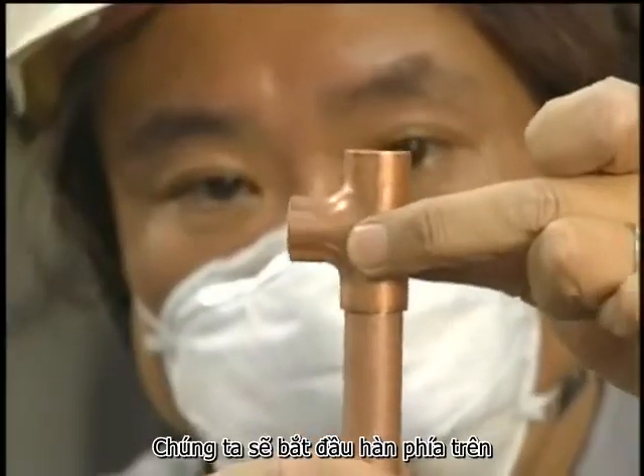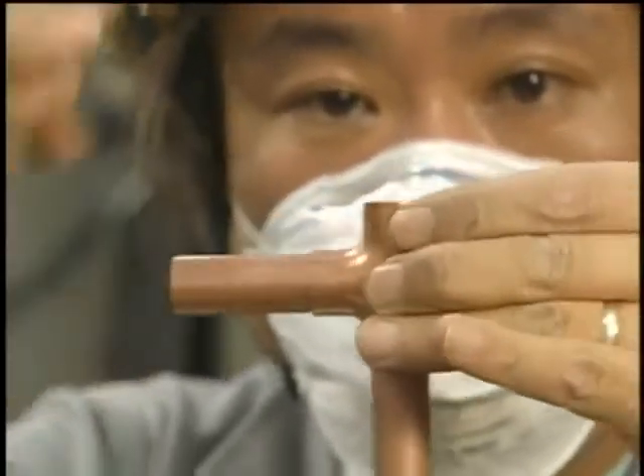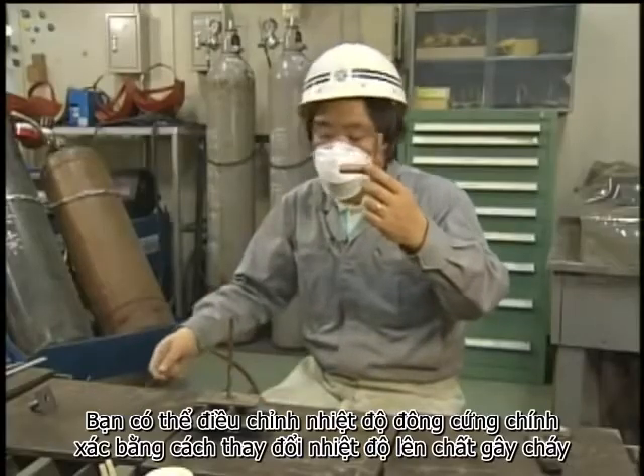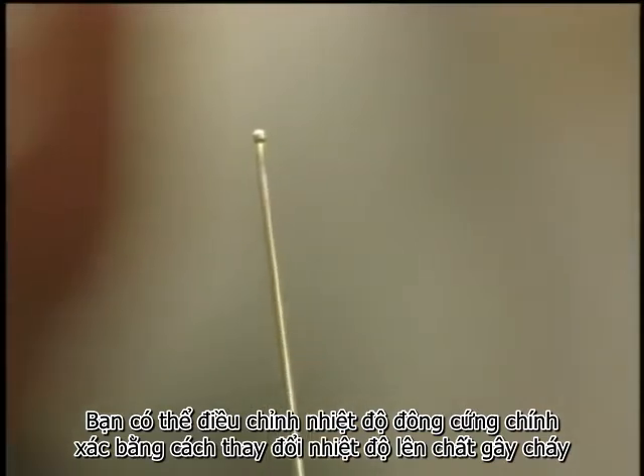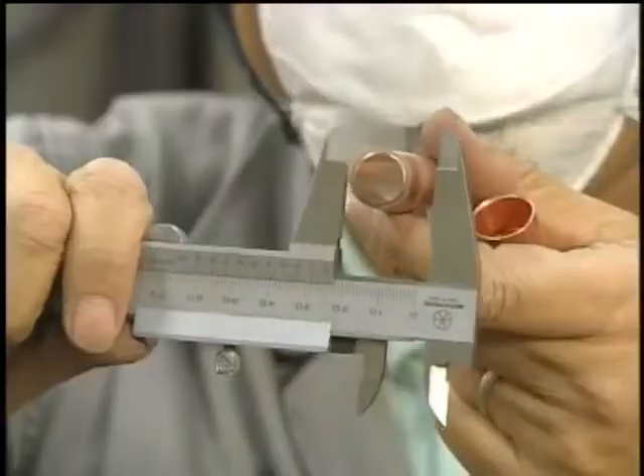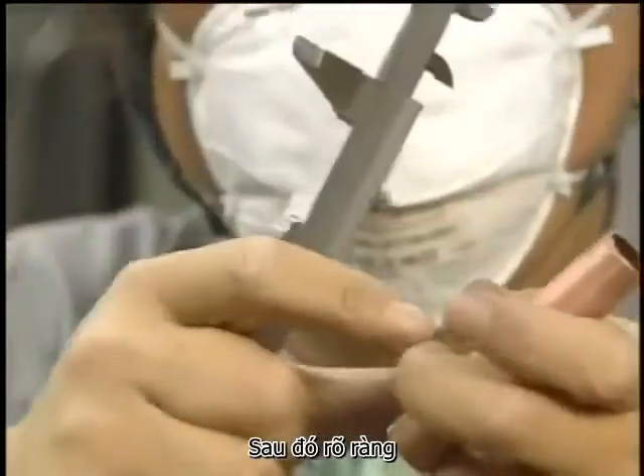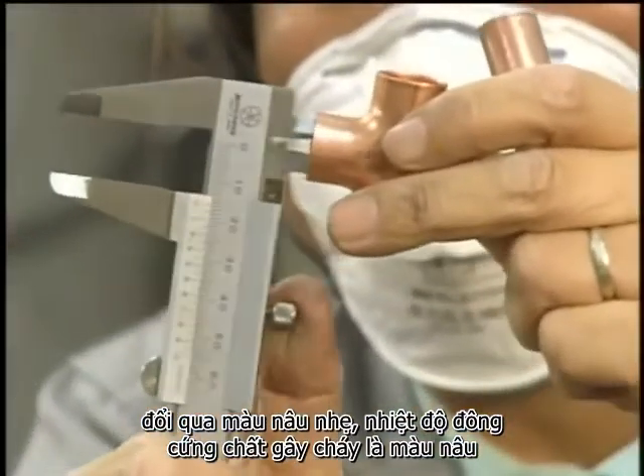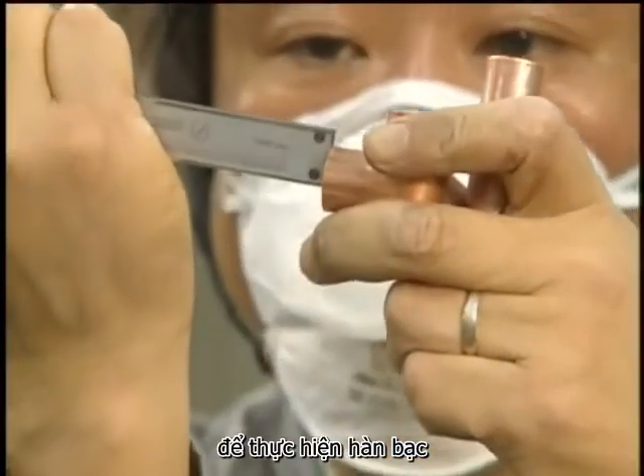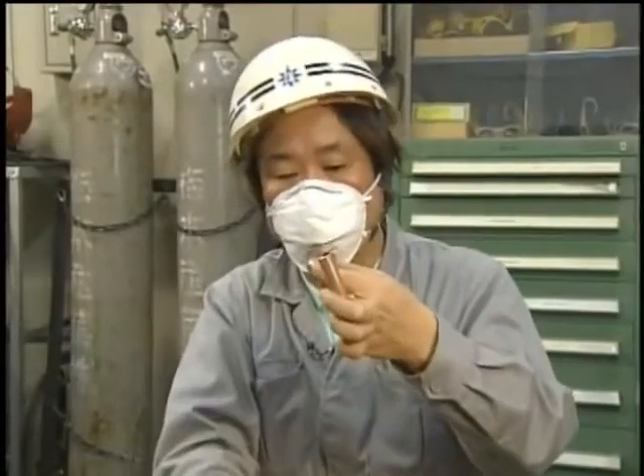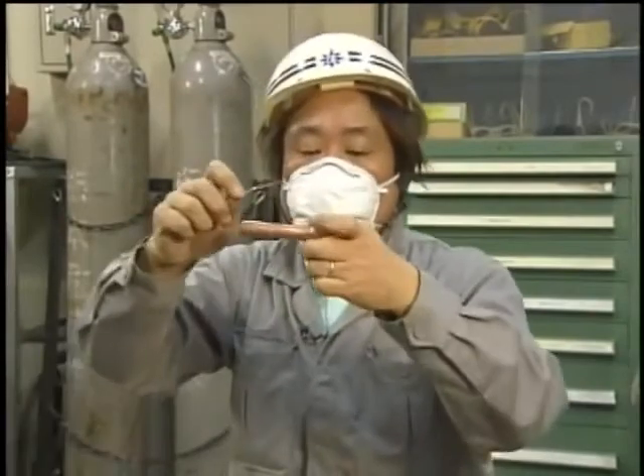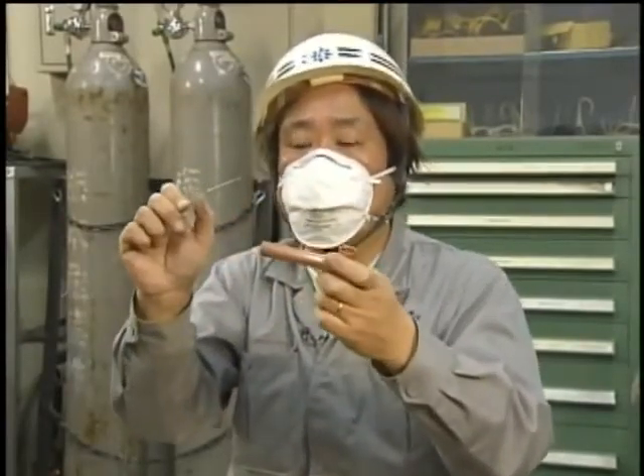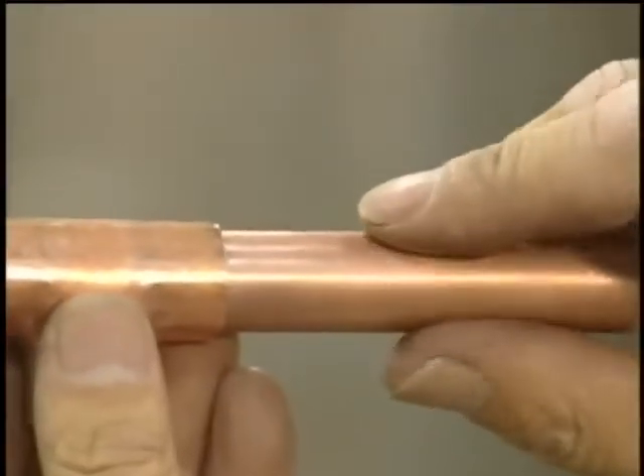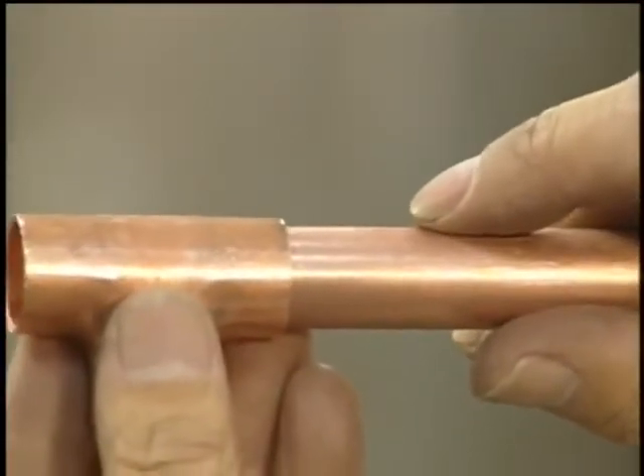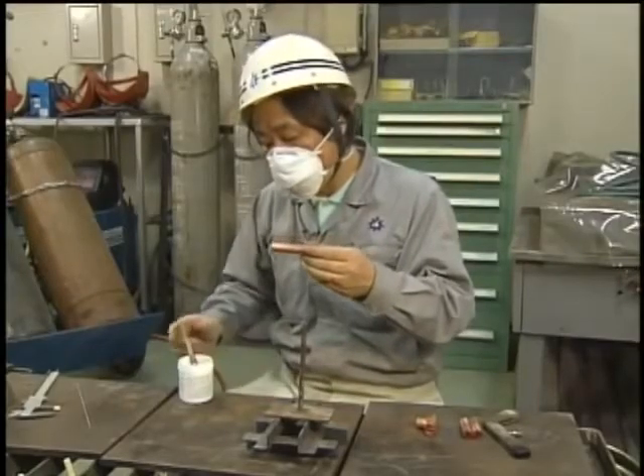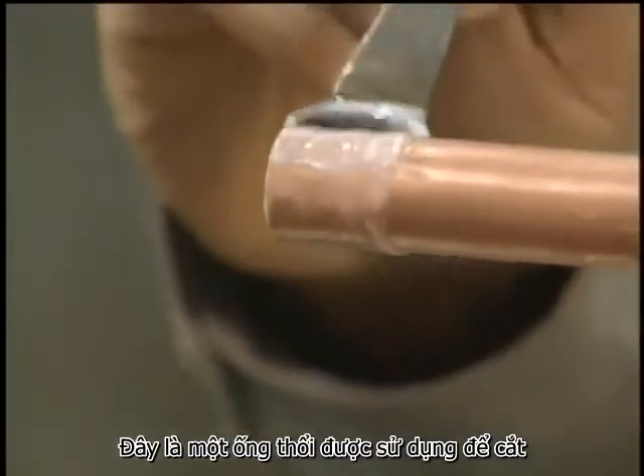When using a T-type joint such as this, apply upward, side, and downward silver brazing to the copper pipe. Before starting, calculate the outside diameter of the pipe, inside diameter of the T-type joint, and the penetration of the insertion volume, so you use only as much brazing as you need. Calculate using a gap of 0.1 millimeters. Before starting the silver brazing, apply flux to the area to be brazed.